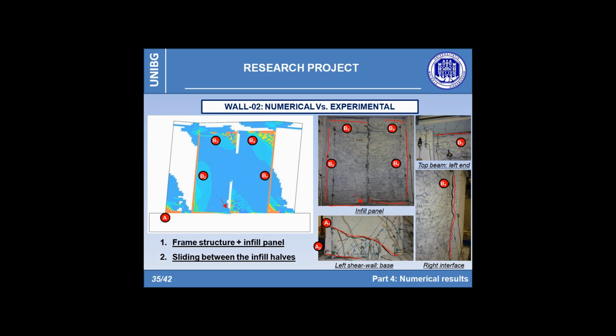Regarding the shear walls, we can recognize damage very close to the previous one, with detachment at the base along the construction joint and cracks affecting the first 50 centimeters in height, due to the combined contribution of shear and bending action. Finally, plastic hinges can be recognized at the end of the top beam, as happened for specimen wall 1.